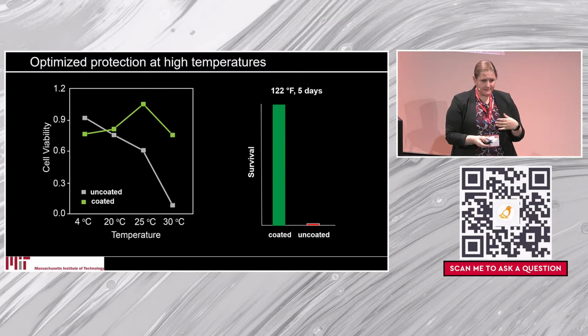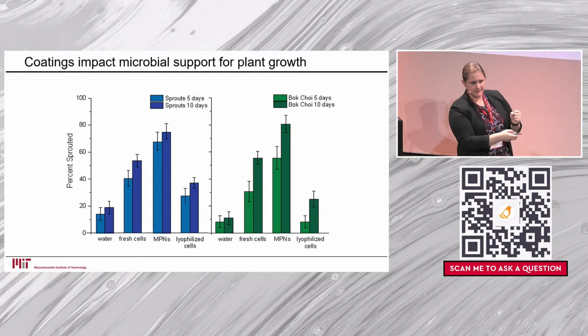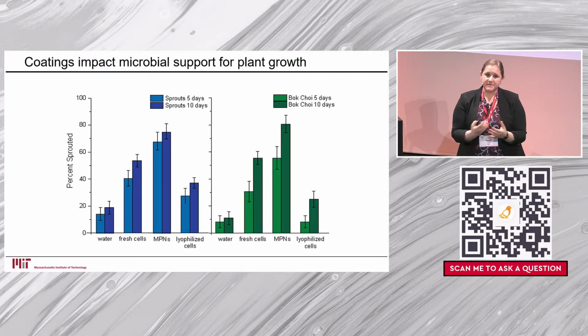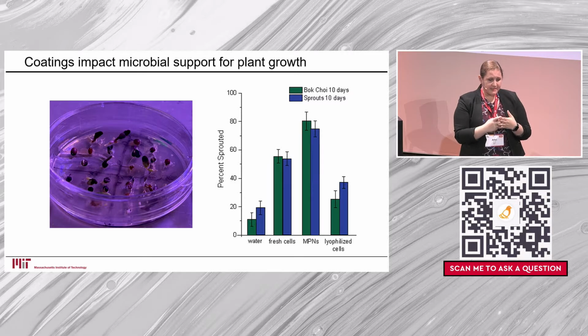And so we wanted to see if these actually helped plant growth. So we looked at alfalfa sprouts and bok choy, and we looked at no cells added, just freeze-dried cells, fresh cells, and our coated cells that had been stored at 50 degrees for 5 days. And what you see here is a clear impact of our coated cells. We can see statistically significant improvement in growth for both of these crops. And we can see here that when we compare them side by side for 10 days, we get very similar efficiencies, even though they're very different crops.